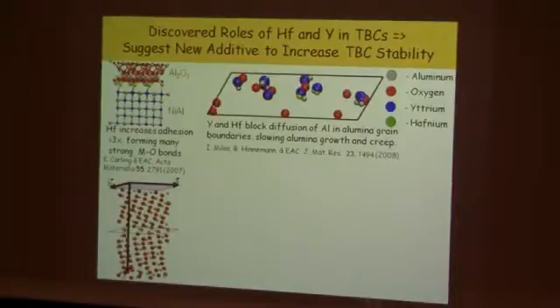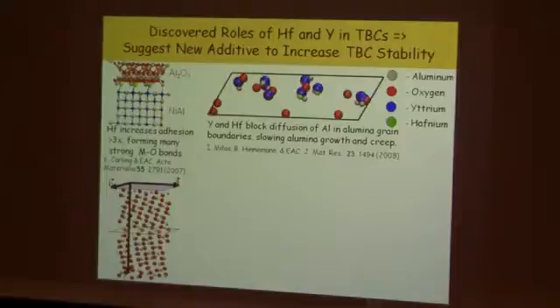We also found out that when the alumina grows, it makes polycrystals. What a polycrystal means is you have a bunch of crystals that are coming together, they don't quite fit, and they have a bunch of room between them that are called grain boundaries. There are grains and there's a boundary between them. And this is an example of a grain boundary in alumina, aluminum oxide. What I'm showing here is a cross-section of that grain boundary.